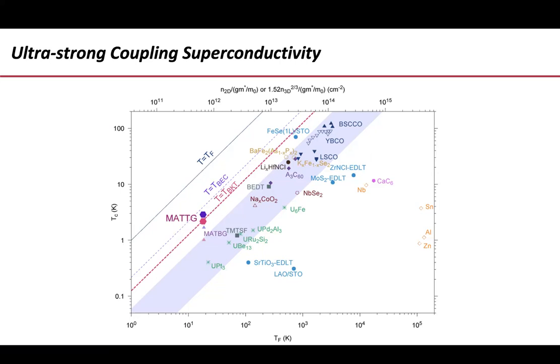Well, magic angle twisted bilayer graphene and magic angle twisted trilayer graphene are here, okay? They have the strongest pairing glue that we are aware of in any superconductor, okay? They have Fermi temperatures which are many orders of magnitude smaller than aluminum, for example. Well, the TCs are actually higher than aluminum. Okay? If the cuprates had the pairing glue strength that magic angle twisted trilayer graphene has, they would be above room temperature superconductors. And we do not understand what makes electrons in magic angle graphene pair so strongly, given how extremely dilute the system is. Okay, we're talking about one or two carriers every 10 nanometers square, roughly, right? That's why density is so dilute.